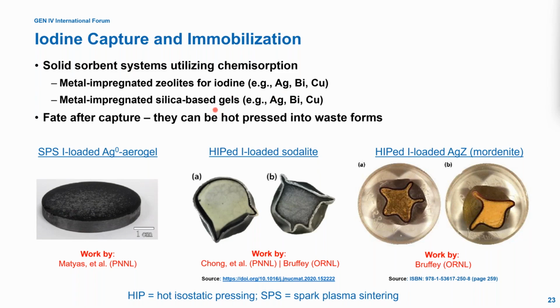There's also metal impregnated things like silica aerogels, silica aluminosilicate based aerogels that have been metal impregnated with things like silver, bismuth, copper, as well as a wealth of other different metals. And then after these have been loaded with iodine, they can be hot pressed into waste forms. So this is an example of a spark plasma sintered iodine loaded silver functionalized silica aerogel by Matyas here at PNNL. This is the largest puck that he was able to make.